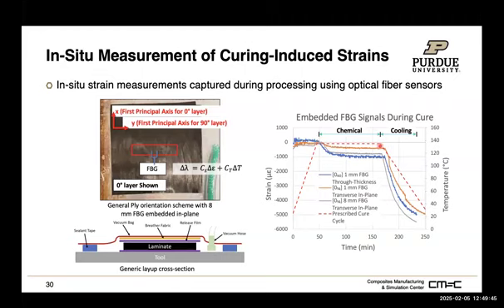As I mentioned earlier, with those models we've talked about so many times, you have the chemical shrinkage because of cross-linking. And we indeed see that from the fiber optical sensor. And definitely you see the strain being developed because of the cooling. That is more obvious, but the chemical reaction can also induce shrinkage.